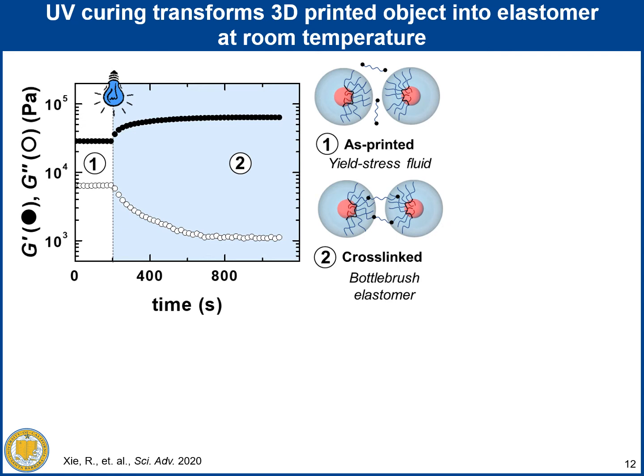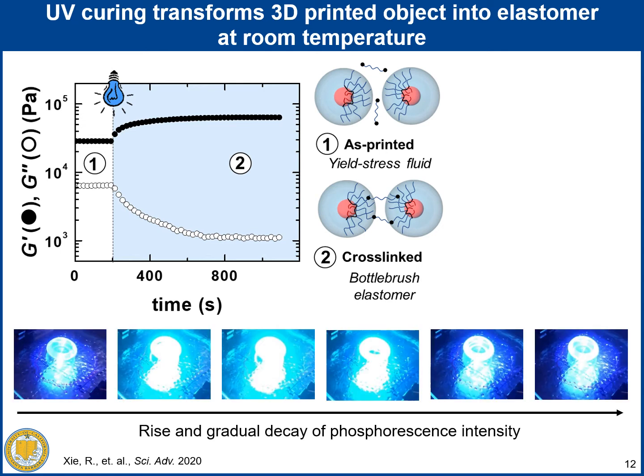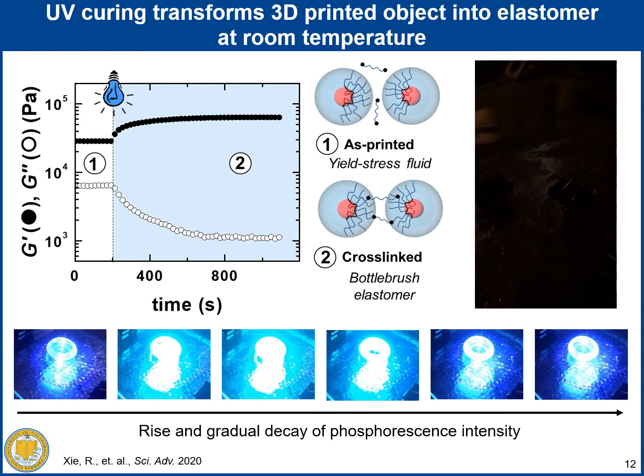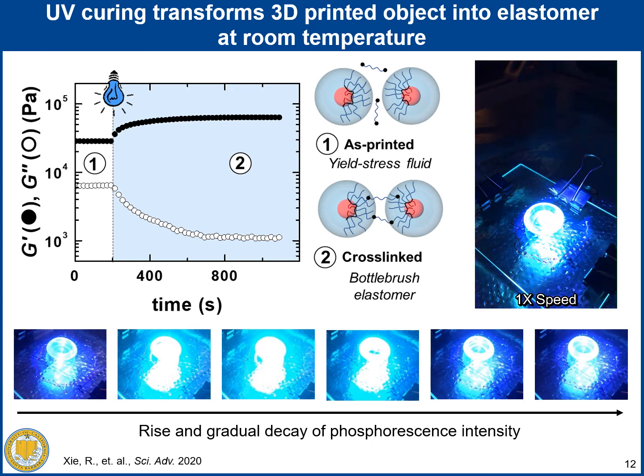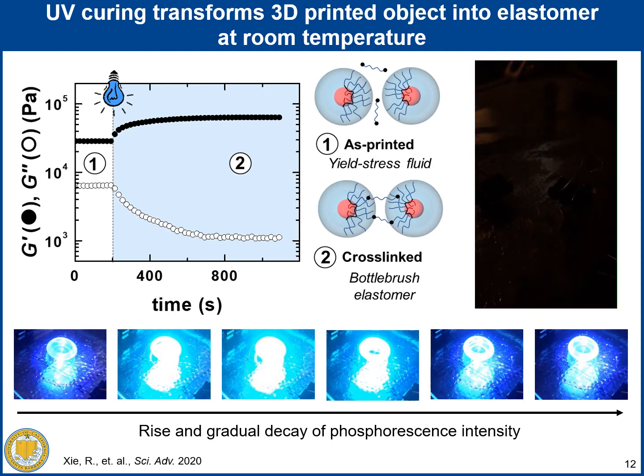The as-printed soft solid can also be transformed to the bottlebrush elastomer after UV curing. The completion of the UV curing is not only indicated by the plateauing of the shear moduli, but also by tracking the rise and gradual decay of the phosphorescence intensities. The video shows the entire UV curing process of the 3D printed bowl, which takes about 30 minutes to finish in real time. But here I have sped up the video for convenience.